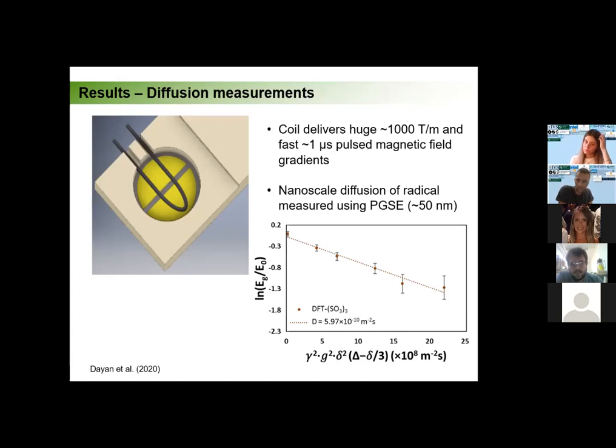And if you remember from the first slide, it means that the energy levels there are different and they have different frequencies. It's kind of similar to the pulsed magnetic field gradients they use in MRI. Because we have a small sample and a small resonator, we can deliver huge gradients, and we can do them at a fast time, 1 microsecond. And that allows us to measure very, very small diffusion distances, around 50 nanometers.